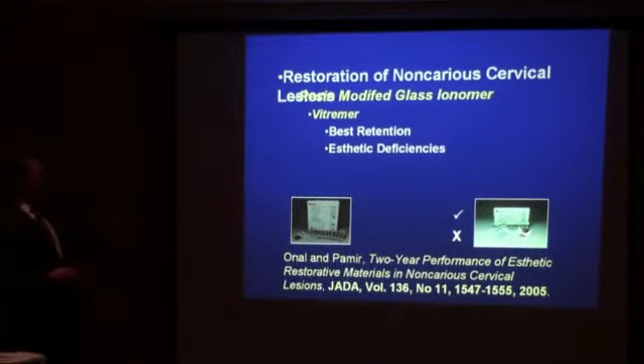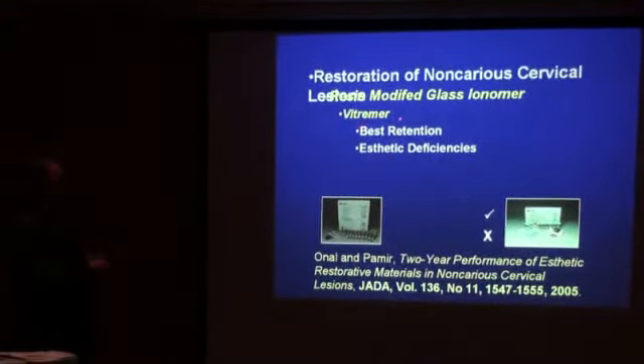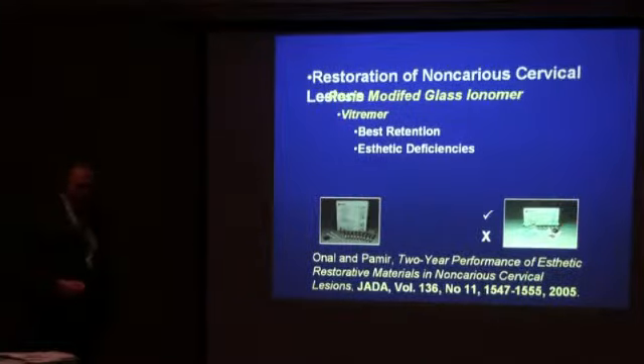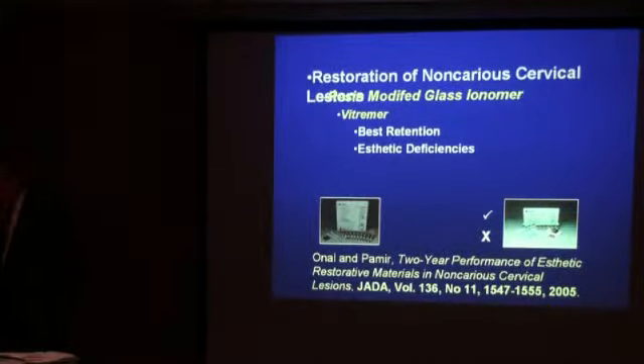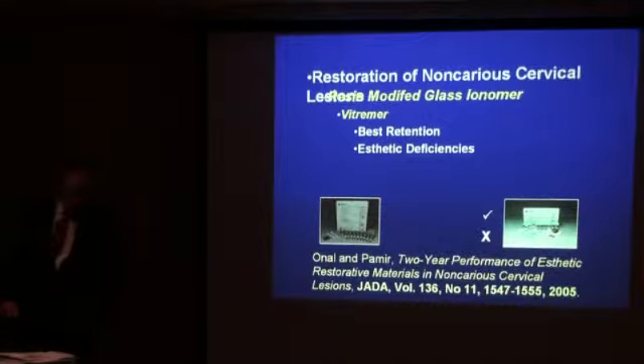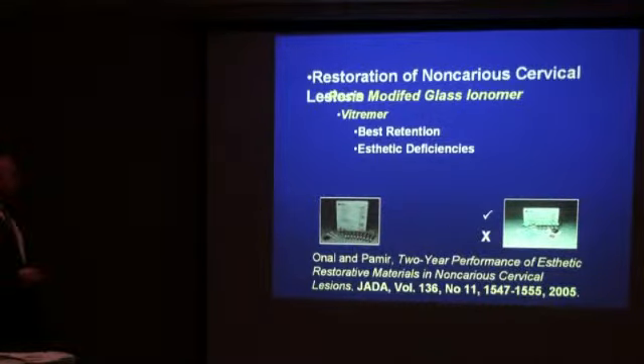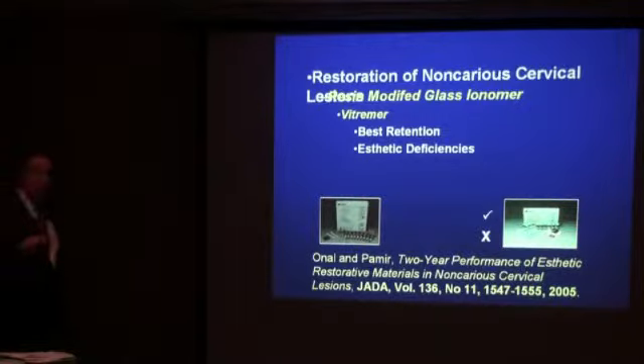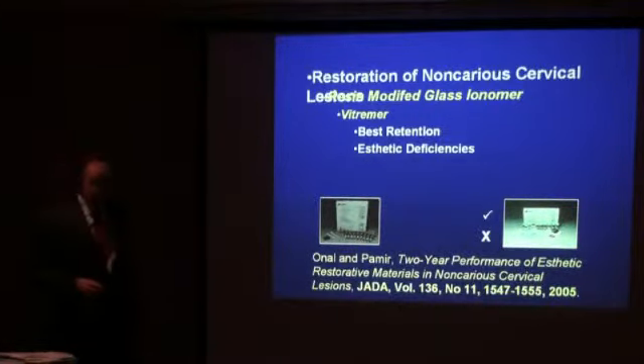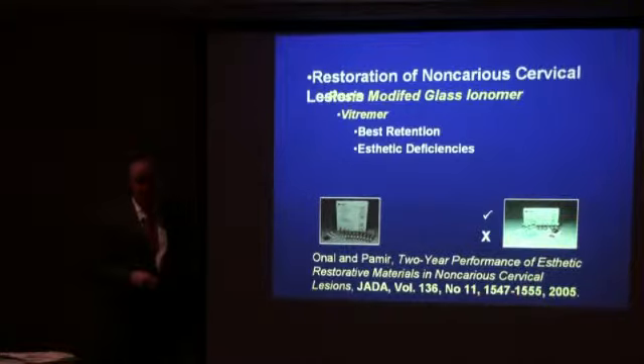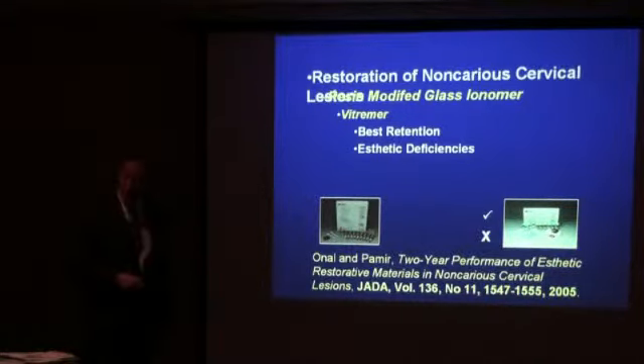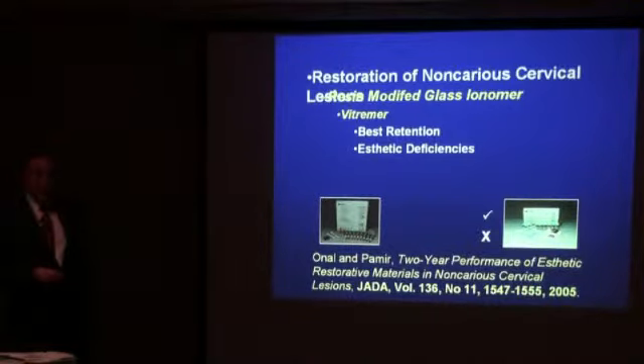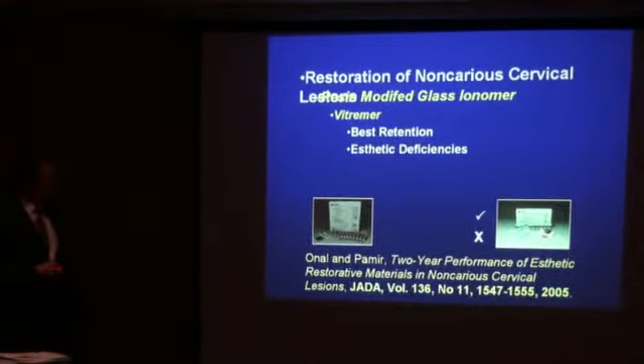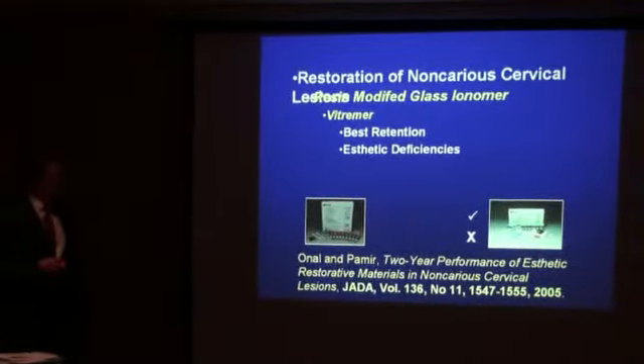And so what we found with this study, they evaluated the material Vitremer, which is also a 3M product, but it's a very old product. It's probably been on the market for 20 years. Well, Vitremer had a perfect retention rate. Every one of the Vitremer restorations was present after 2 years. The problem was in the aesthetics. Vitremer doesn't polish very well, so it didn't have a smooth luster. The shade match was terrible in several cases. It's hard to shade match Vitremer. And so it got a bad grade in terms of aesthetics.